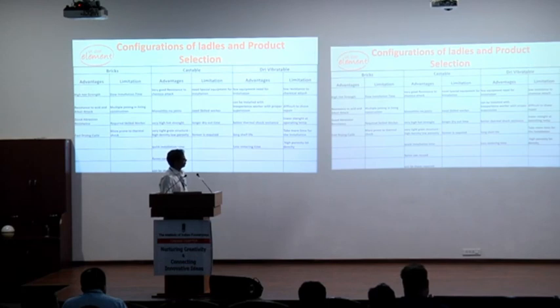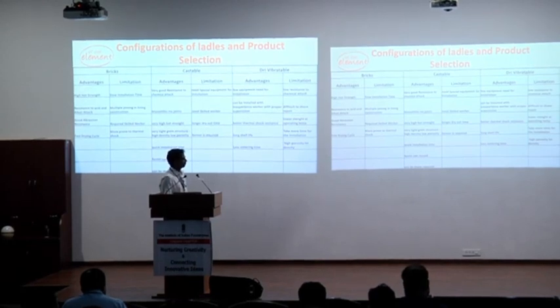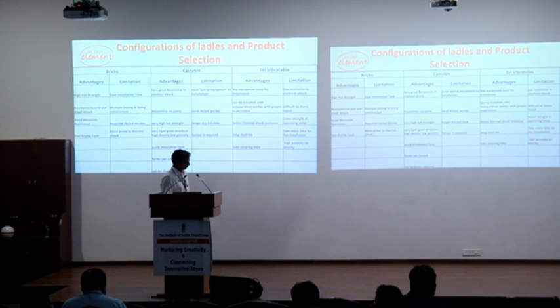Limitations are low resistance to chemical attack. It is very hard to shave repair after a period of operation if you want to repair. Low strength at operating temperatures. It takes more time during installation because you have to do it like a coreless furnace, forking and ramming, and it has a lot of porosity because of low density, which leads to a lot of slag attack.